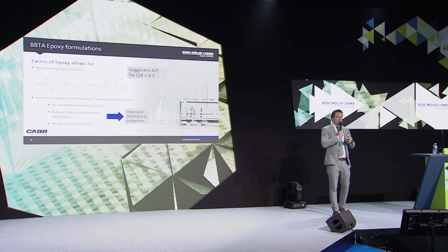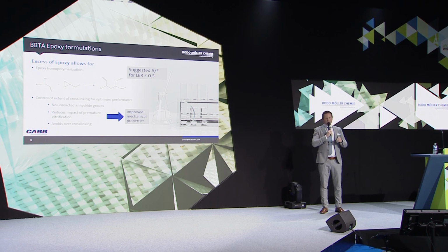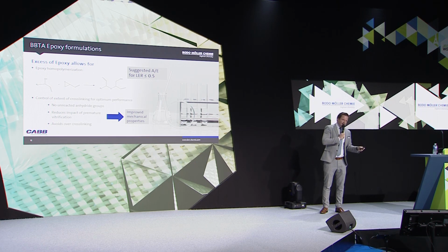To give more detail, you get the best performance with a ratio of roughly 0.5 anhydride to epoxy. So you really need a high excess of epoxy resin to achieve two things. The one thing is that you promote homopolymerization of the epoxy resin, which leads to very good mechanical properties because a different kind of polymeric network is formed. The second reason for an excess of epoxy resin is that you make sure you don't have any unreacted anhydride groups. Also, you avoid over cross-linking in your system, which might be a problem, and you reduce the impact of premature vitrification.